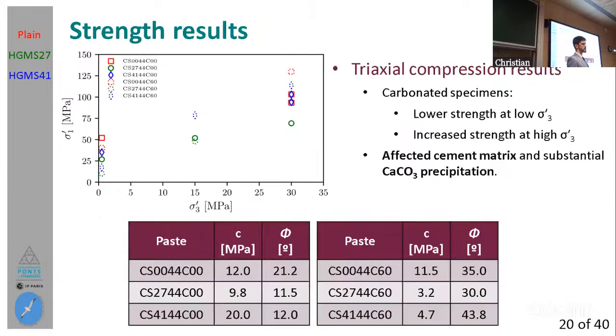If we now want to take a look at the results of strength obtained on both unconfined and confined compression tests, here I show you the results of unconfined compressive strength, which I have shown you before. The solid line points correspond to the non-carbonated specimens, and the dotted line points correspond to the carbonated specimens. Then you will see that we have this lower strength at low sigma 3, but then as we increase the sigma 3, we have a larger extent of the increase in the frictional behavior of the cement paste after carbonation, which can be seen here to here.